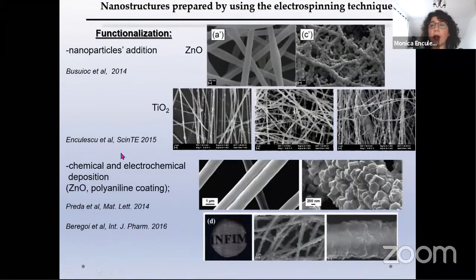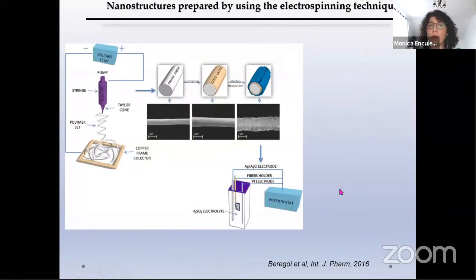Further, there are other types of functionalization, chemical or electrochemical deposition. We can cover these fibers with a layer that allows us to functionalize and use further the fibers. So in this way, we can coat the fibers with zinc oxide, or we can coat the fibers with polyaniline, and by doing this different type of functionalization, different types of applications are thought for these nanofibers.